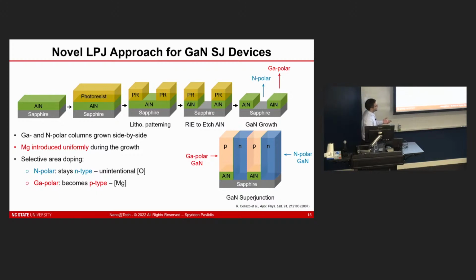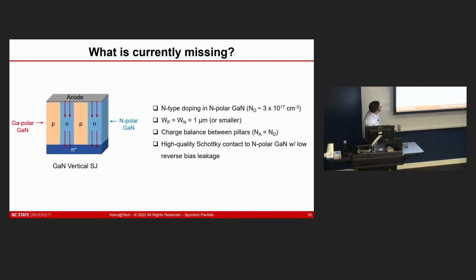And this is really a very different approach compared to what you see in conventional fabrication techniques with implantation and so on. We can do this in a single growth step. And as a result, that also leads to the ability to scale this down even further. We can do a single litho. You can use something like EBL, for example, in the future, and get submicron features and not have to worry about layer-to-layer alignment and multiple lithography steps along the way.